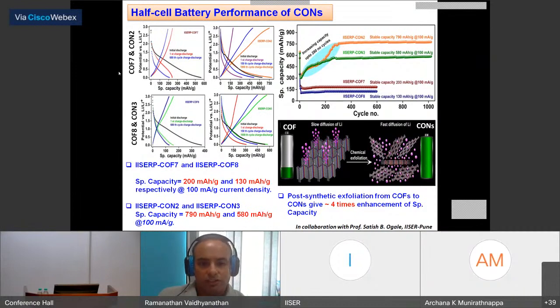So we have done the charge-discharge studies on the COF versus CON, and this is for the COF, and this is for the corresponding CON that is generated by chemical exfoliation. And this is for the next COF, and the CON corresponding to that. So I would draw your attention to this part of the graph where you can see the specific capacity of the anode derived from these COF-based or CON-based ones, and you can see the comparison. So the COFs are giving a specific capacity in the order of 200 milliamp hour per gram, whereas for the CON, it rises to a value as high as 4 times what the COF is able to give, and it goes up to almost 800 milliamp hour per gram.